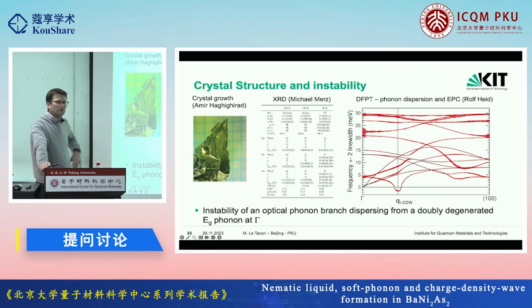In a sense, it really contrasts, for instance, with the instabilities that you would have in niobium diselenide or a classical charge-density wave system. Even this lanthanum silver antimony compound that we measured here, where you can nicely see the instabilities and the soft modes and follow them as a function of temperature.